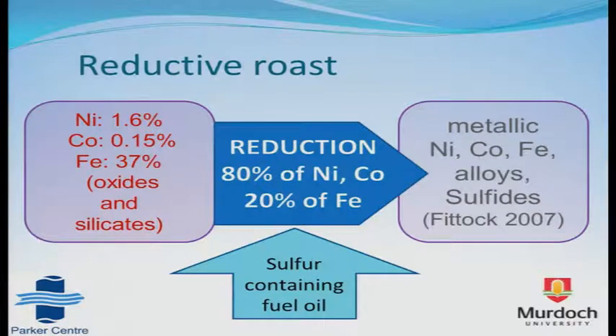And so to look at the material that I'm studying, the solid material, I have to go back one step and look at the reductive roast. So the laterites, in which the nickel and cobalt are present mainly as oxides and silicates, are roasted under reducing conditions. And in this step, 80% of the nickel and cobalt are reduced to the metallic state. And because of the presence of significant amounts of iron, there's also a significant amount of metallic iron reduced, approximately 20% of it. So the nickel and cobalt are mainly present as alloys with the iron. Also, because of the presence of sulfur in the fuel oil used in the reduction, there are also some sulfides being formed during this step.